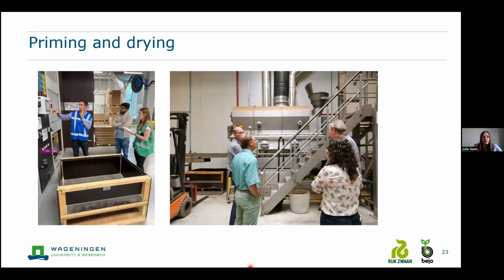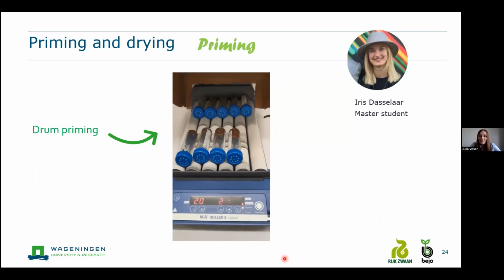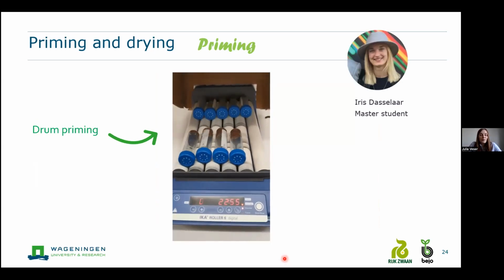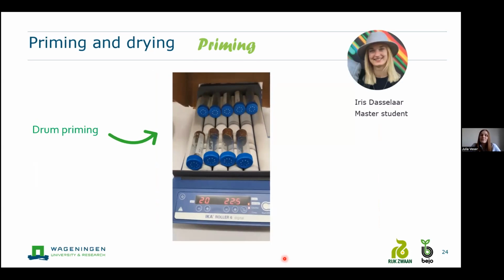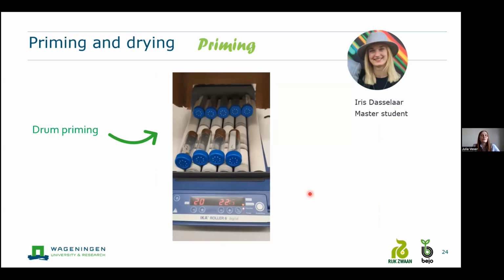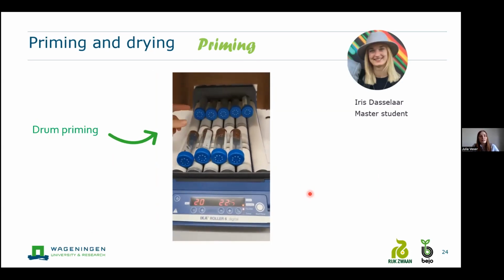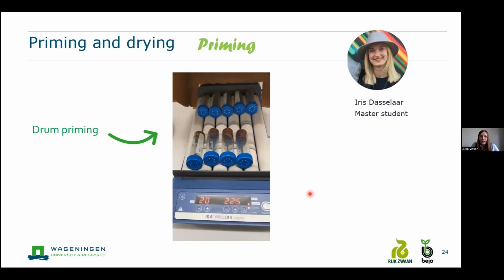Here you see some drying equipment. One typical drying is the seeds drying in hot air, and the other thing would be a typical fluidized bed dryer. For us, I worked together with my master student, Iris Dasselaar. We first developed a priming or hydration method, and therefore we use drum priming. That means we add a certain amount of water and a certain amount of seeds in these little tubes, and then they are turned slowly for some days until the seeds are really fully imbibed and have started this second phase of metabolism activation, but have not germinated yet.